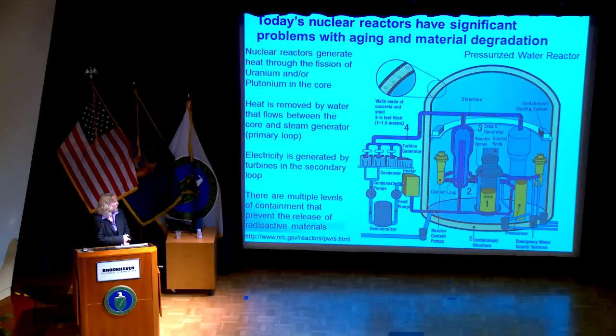We'll discuss some of them in the core on the next slide, but I want to point out that a very important barrier is the reactor pressure vessel. This will be the subject of most of my presentation today. In addition to the reactor pressure vessel, another barrier for the release of radioactive materials is the outside containment structure, which is a concrete and steel wall that's 3 to 5 feet thick. So there's layers of barriers to the release of fission products, and we'll be discussing the core and the reactor pressure vessel. And all of these systems, the piping, the pressure vessel, the core, they're all subject to aging and material degradation.